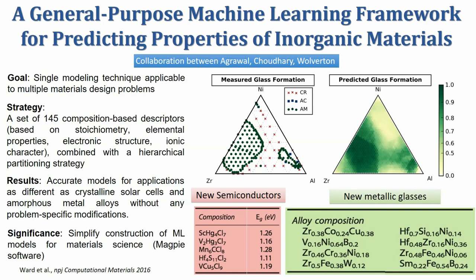For the glass forming ability, we kind of withheld this system, the nickel, zirconium, aluminum system, from the training data set, and not just this ternary system, but also the 3 binary systems. So the training data did not have any nickel, zirconium, aluminum, and aluminum, nickel compositions in the set. And then we asked the machine model to just fill the space, and you can see that it is a reasonably good match with the experimental. And some of these have been confirmed experimentally in collaboration with SLAC and NIST.